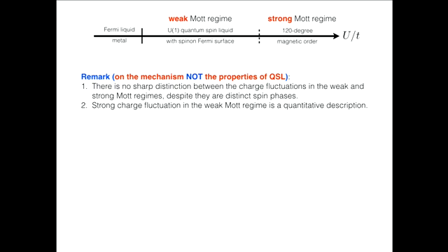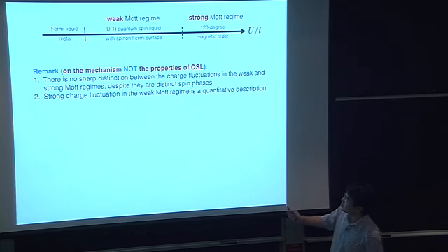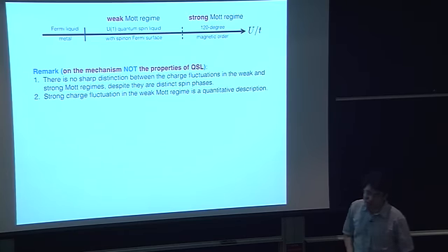So I want to make a few remarks on the physical mechanism for this quantum spin liquid, instead of a physical property of this quantum spin liquid. In fact, there is no sharp distinction between the charge fluctuation in this weak Mott regime and strong Mott regime, despite that there are different spin phases. So the second remark is that the charge fluctuation being strong in this intermediate regime, in the weak Mott regime, is only a quantitative description of the charge fluctuation. It's not a qualitative description.